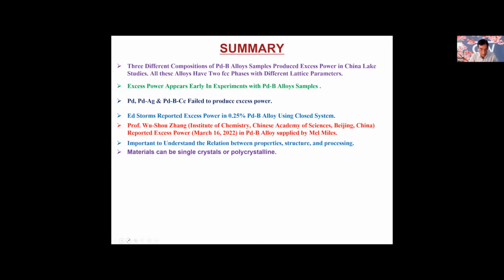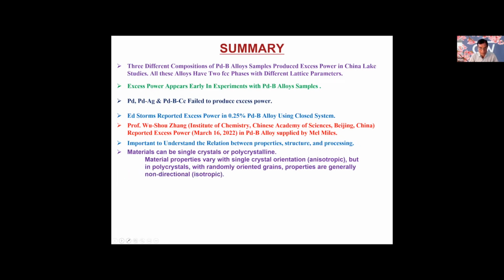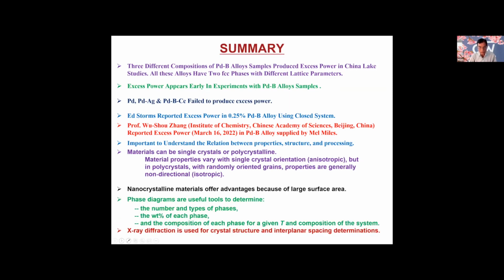Materials can be single crystal and polycrystal, but sometimes the preference is to have a single crystal, because then you can pinpoint some of the effects more easily. Material properties vary with single crystal orientation, which is what we call anisotropic. In polycrystal, which has randomly oriented grains, properties are isotropic. Nanocrystalline materials offer advantages because of the surface area. And phase diagrams are a useful tool to determine the number and types of phases, weight percent of each phase, and composition of each phase for a given temperature and composition of the system. And we normally use X-ray diffraction to find the crystal structure and interplanar spacing. With that, let me wrap up.